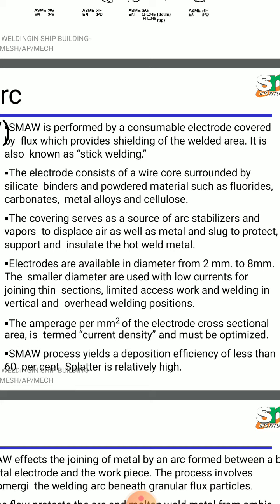Electrodes are available in diameters of 2 mm to 8 mm. The smaller diameters are used with low current for joining thin sections, limited access work, and welding in the vertical and overhead welding positions. The electrode cross-sectional area in square millimeters, the current density, must be optimized. The SMAW process yields a deposition efficiency of less than 60%, and spatter is relatively high.